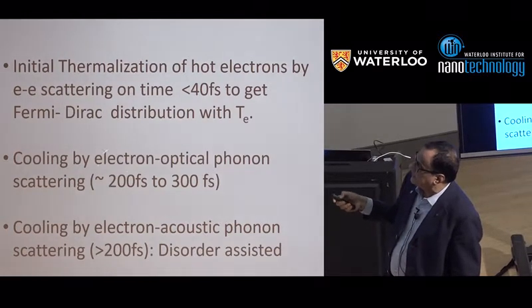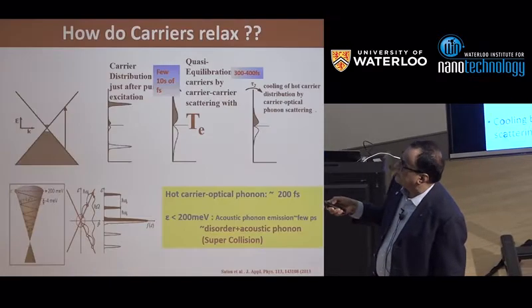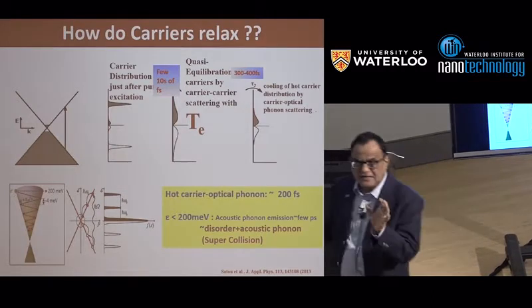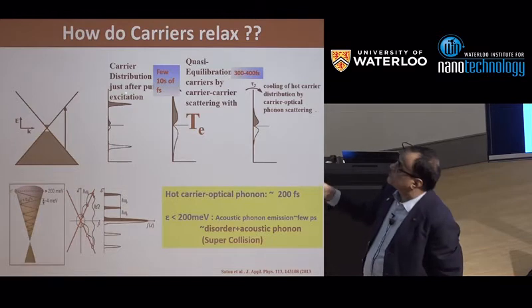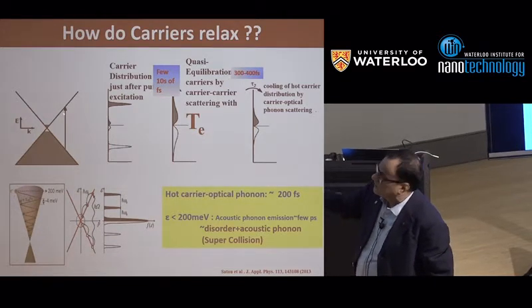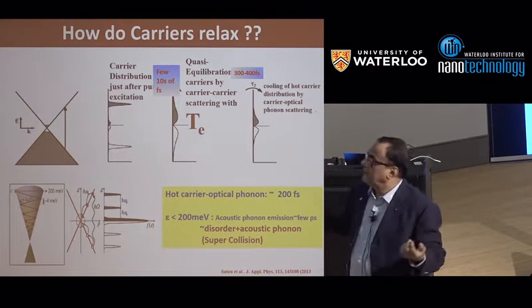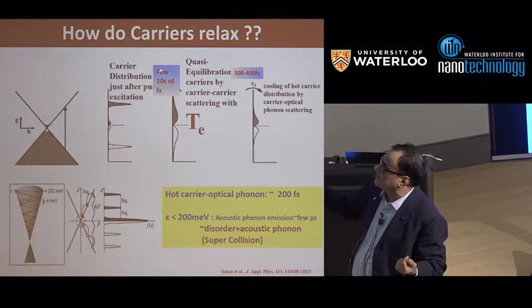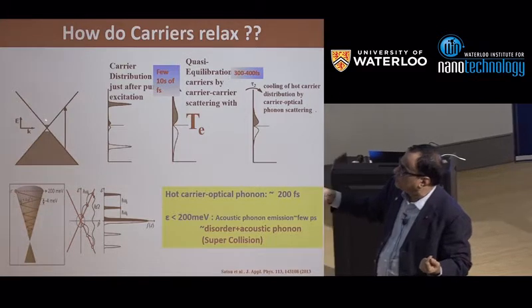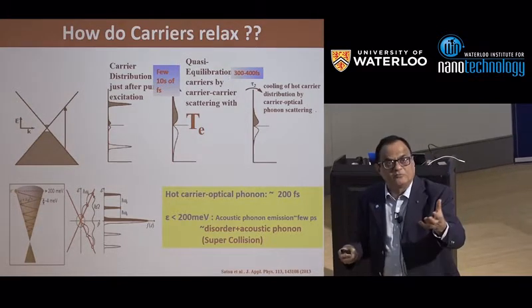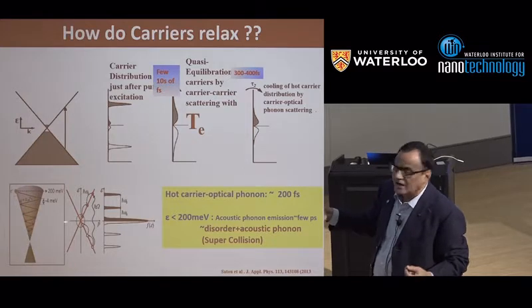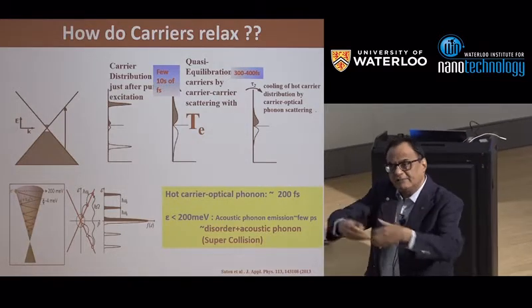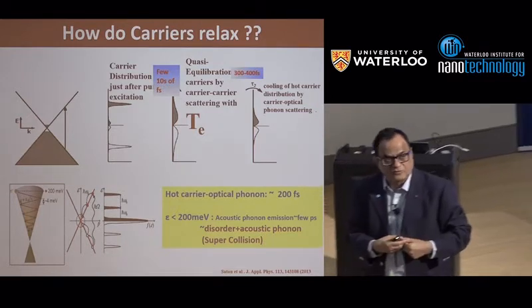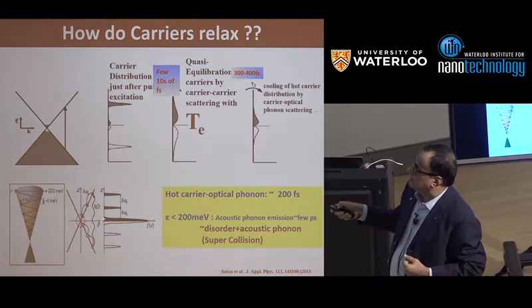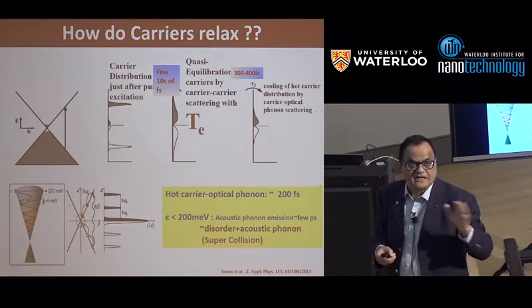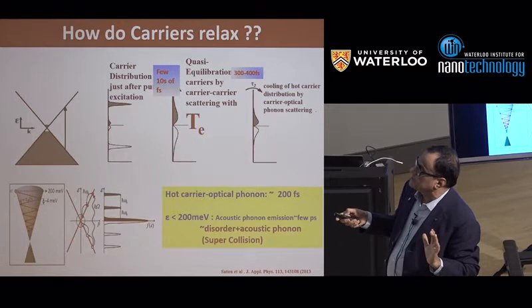So what is happening, let me give you the gist of this. In this analysis, first the photoexcited carriers have a high electronic temperature. They achieve high electronic temperature in about 20-30 femtosecond, and then they cool down to lattice temperature by emitting optical phonons. But when they come very close to the Dirac point, that is not possible. So they start participating with acoustic phonons. And acoustic phonons plus disorder can explain this 5 picosecond relaxation time. So this has all the information which one can take out.